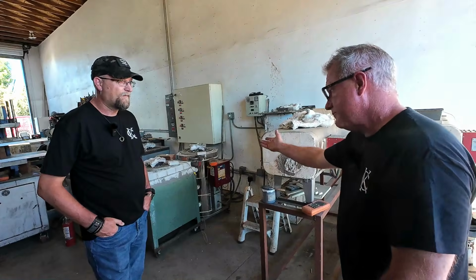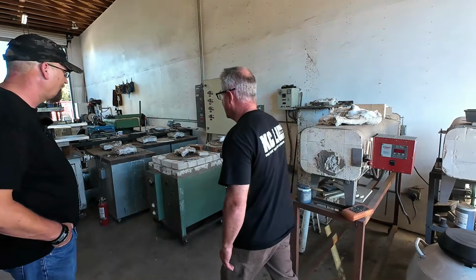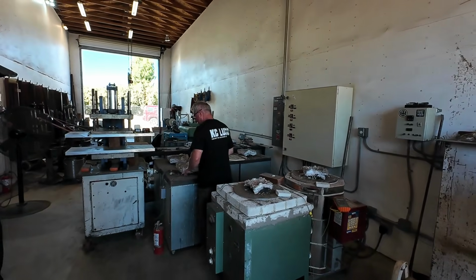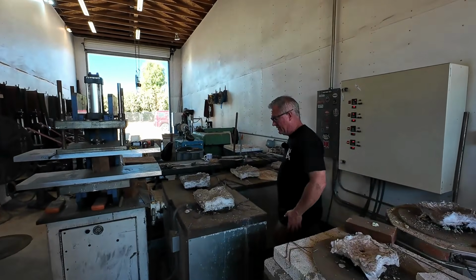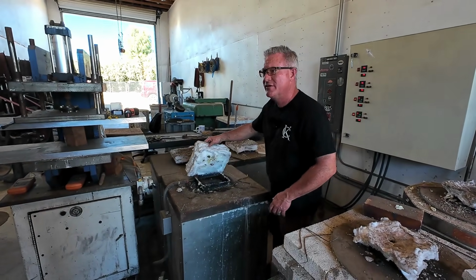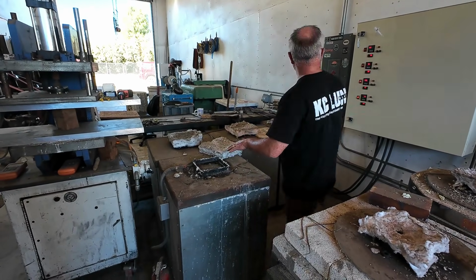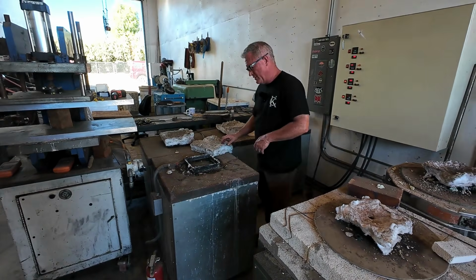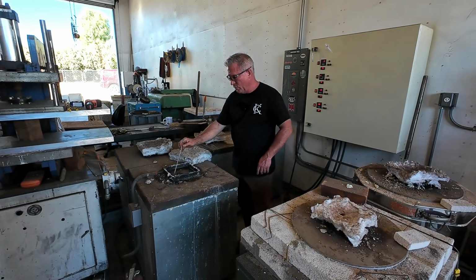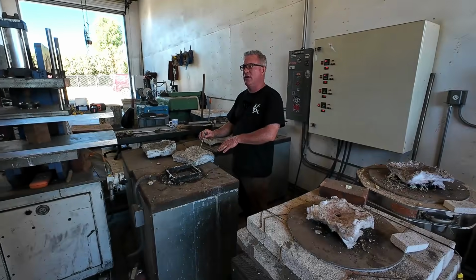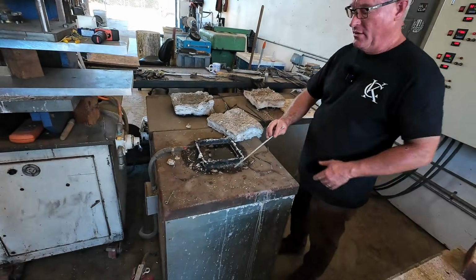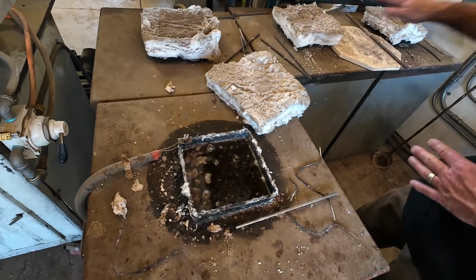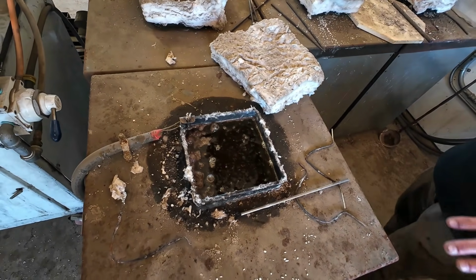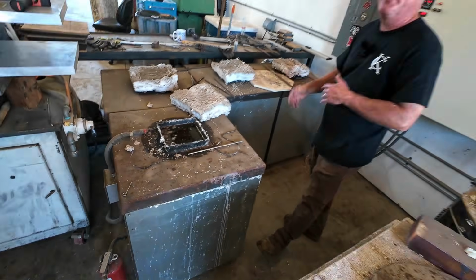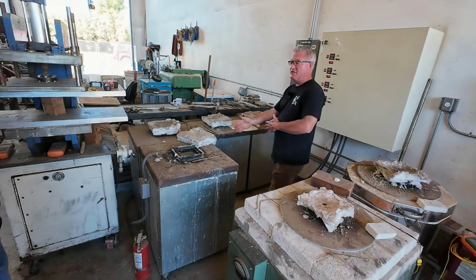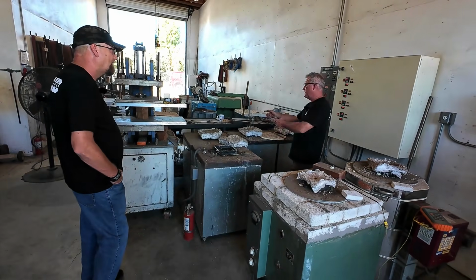Great machine. Then we have the molten salt tanks. These I've designed and built. This is generation, I don't know, 3.0, 4.0, 8.0, something like that. That salt right now is at 523 degrees Fahrenheit. That is molten salt, and that's what the blades get quenched into, quenched and tempered. I have them all running right now, all four. I built these for batch heat treating, for doing large volume. But it's also nice because you've got redundancy. If your tank goes down, that's fine, I've got another one.